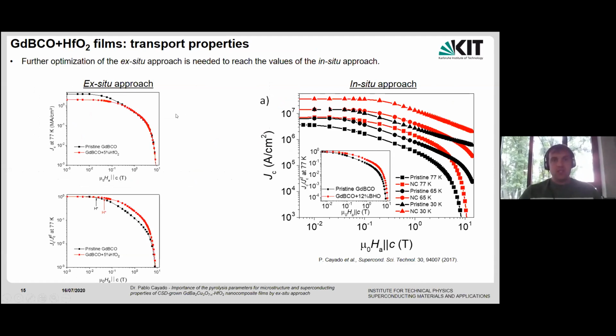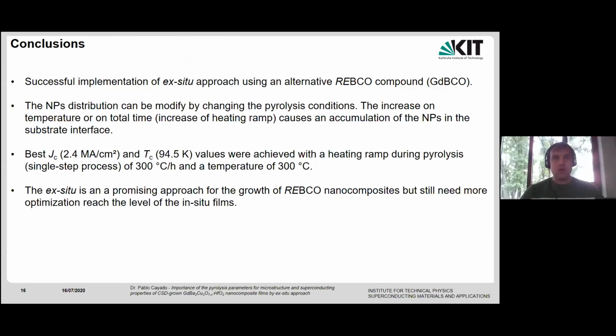So these so-called ex situ films with these in situ nanoparticles show promising results. We have here, for example, an increase of the H star, which means that we can enlarge this single vortex pinning regime. However, this is, let's say, the first step of this process, and we still need to optimize much more to reach the values and the performances of the in situ approach, as we also published in this other paper, because in this case we have much larger values of Jc and also better in-field performances. But this is a quite promising first step, so we still need to optimize, but we are quite happy with these results. And yeah, with this I came to the conclusions.